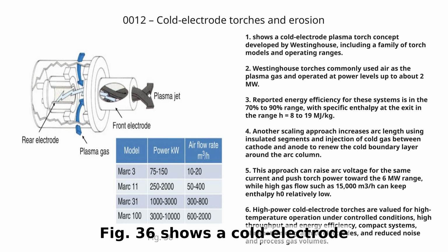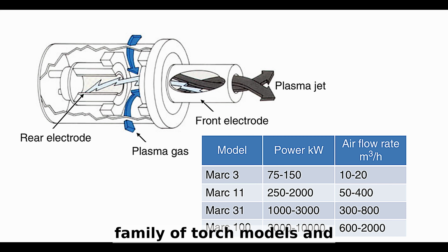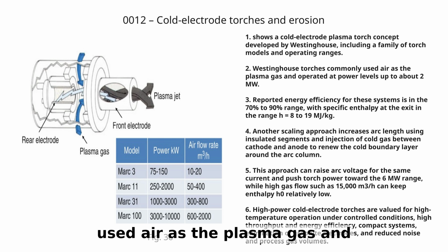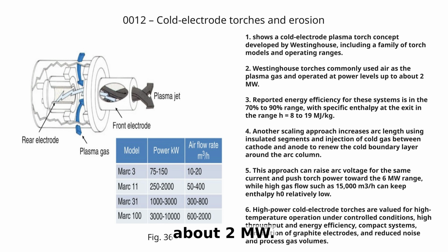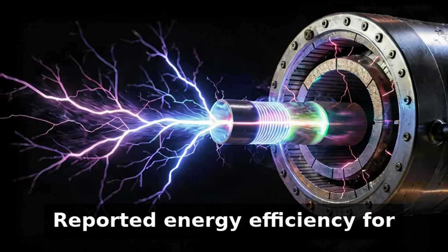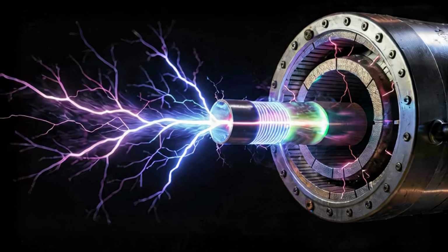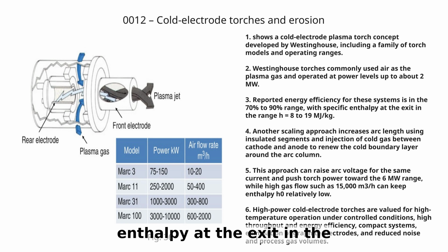Figure 36 shows a cold electrode plasma torch concept developed by Westinghouse, including a family of torch models and operating ranges. Westinghouse torches commonly used air as the plasma gas and operated at power levels up to about 2 megawatts. Reported energy efficiency for these systems is in the 70% to 90% range, with specific enthalpy at the exit in the range H equals 8 to 19 megajoules per kilogram.